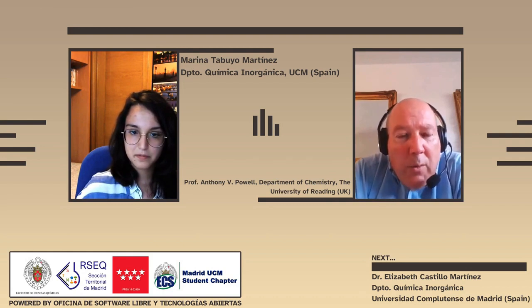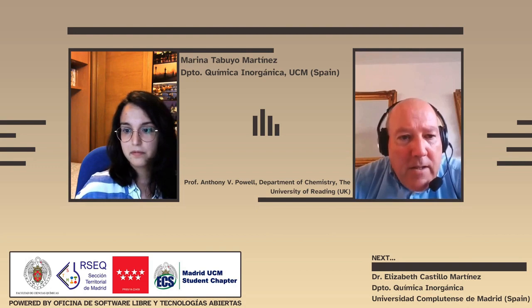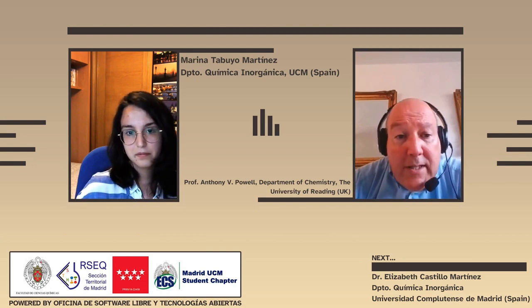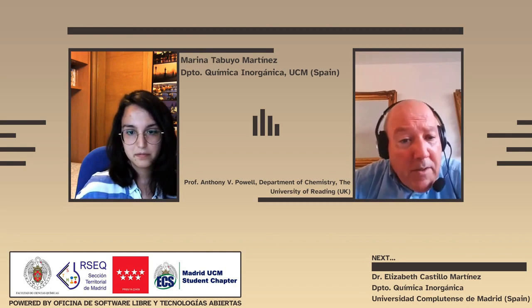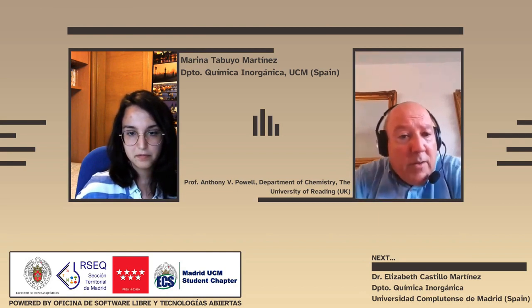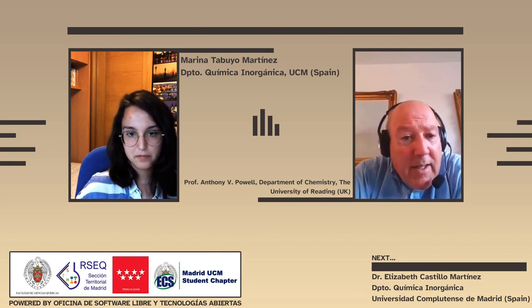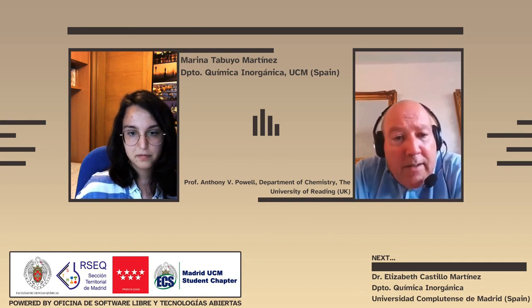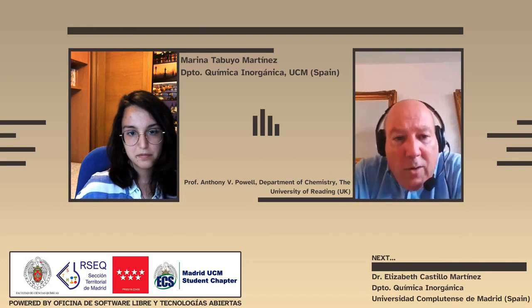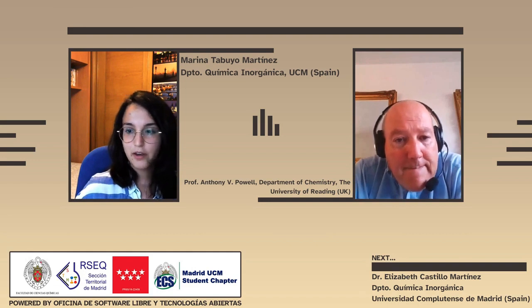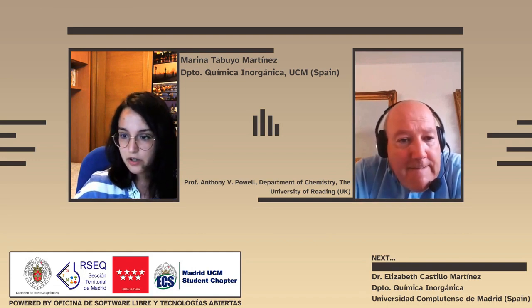And where we've struggled with the skutterudites is actually finding a solder that operates at the high temperatures where we'd want to use a module. So although we've got quite good performance, if we went up another 200 degrees, the performance would probably be even better. But unfortunately, our solder melts by the time we get to that point. And it's a question of finding the right solder in order to get both good mechanical contact and good electrical contact.